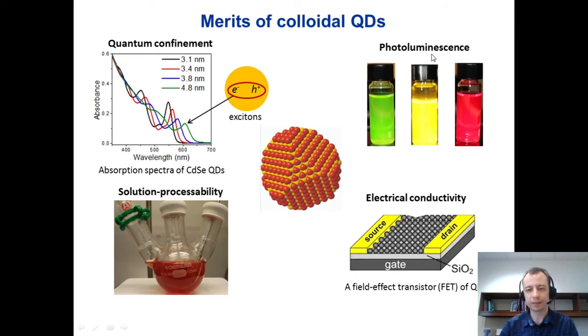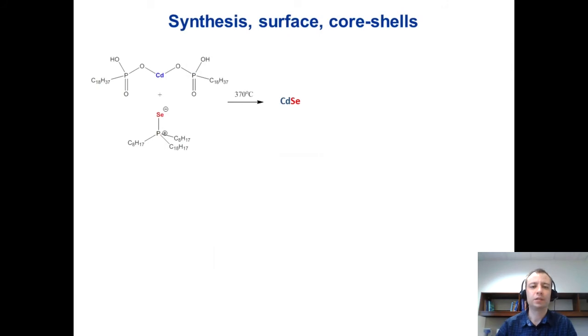Second, photoluminescence. Again, unlike their parent bulk materials, quantum dots are photoluminescent. And we can tune the color of this photoluminescence by tuning the size of the quantum dot as well as its shape and composition. Third, these quantum dots are solution processable. They are produced in routine fume hood syntheses. Finally, these quantum dots can be made electrically conductive for their use in electronic devices like field effect transistors or solar cells.